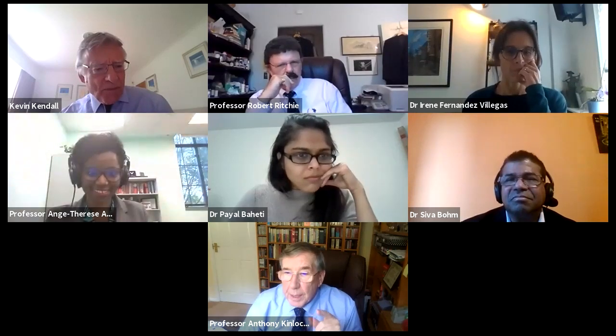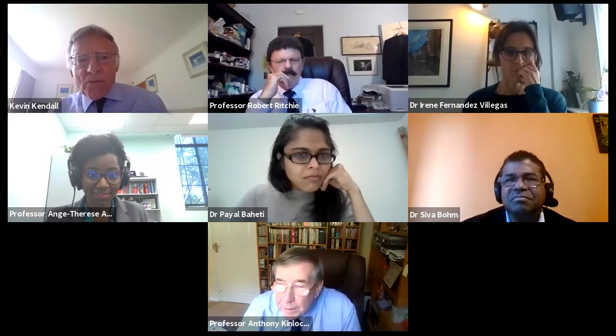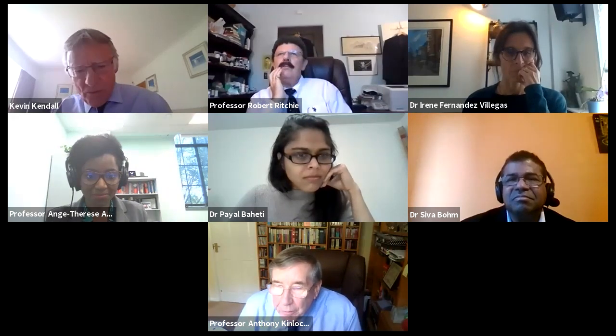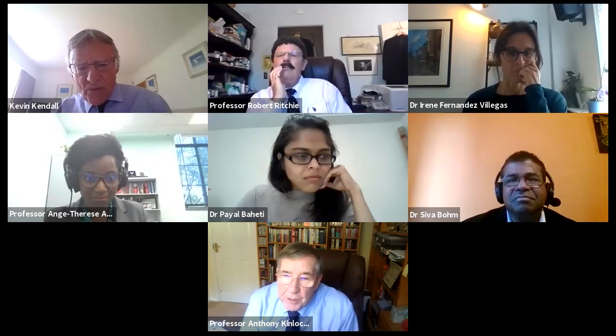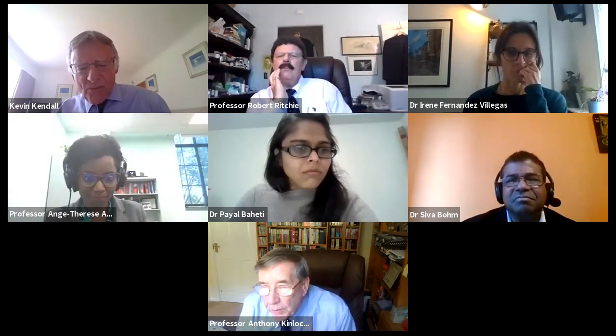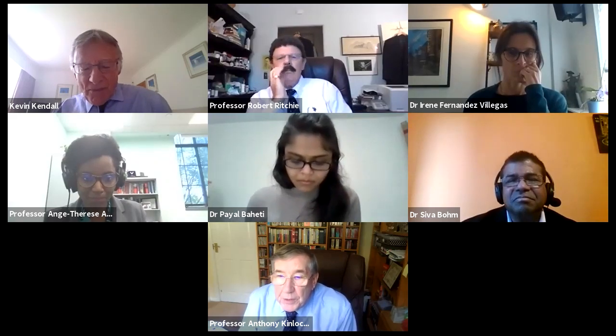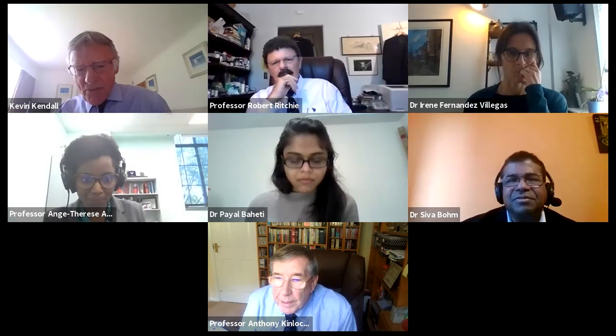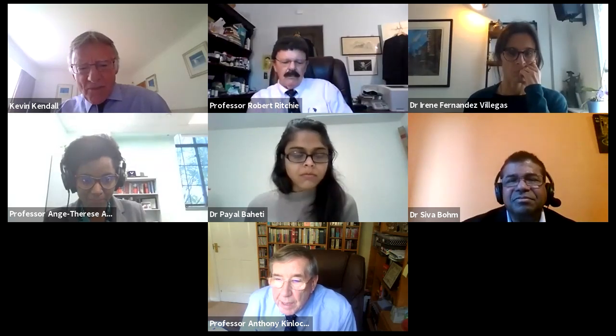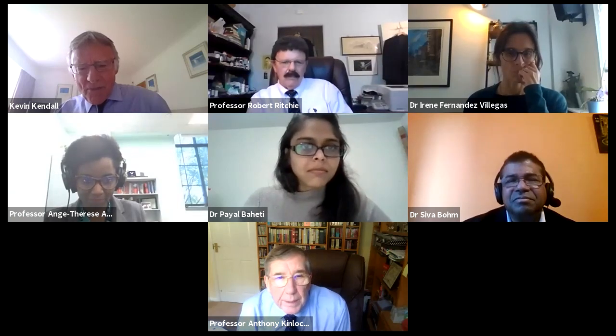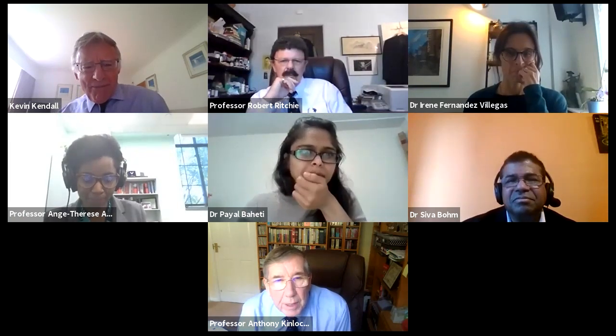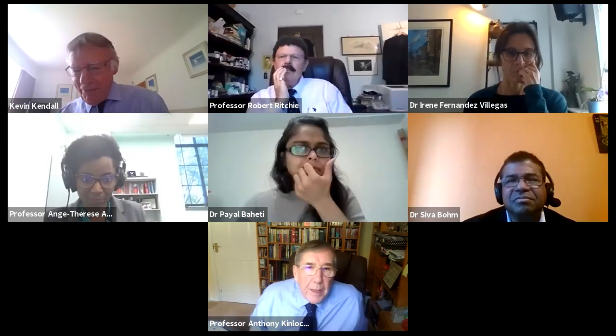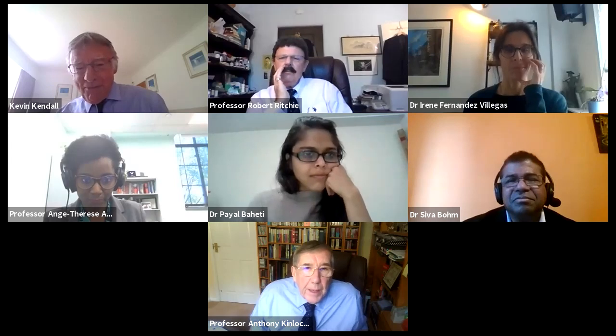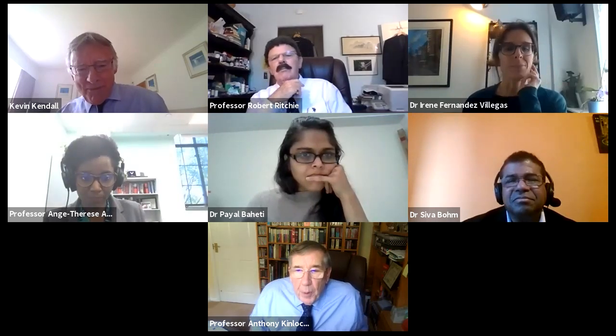Can I interrupt a second there, Kevin? Just to take this further, we have a couple of questions here on this. Mark Gessing comments, for your attention, fracture toughness is different from other material properties such as density, elastic modulus, or Poisson's ratio, because it's not independent of the sample shape or loading. This leads to some of the difficulty in using toughness-based criteria in material selection or engineering design. Now, I know, of course, in the various standards, we try to define K1C and G1C, which is plane strain typically for LEFM, and therefore overcome that. But I think it's an interesting point that Mark makes.